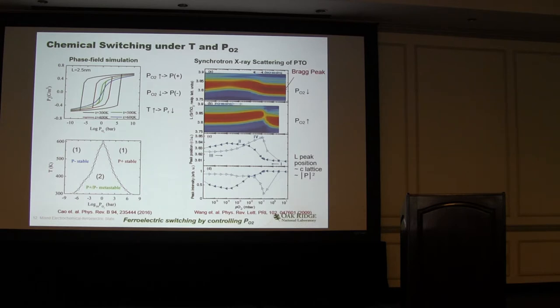this route. So when we plot the peak position and peak intensity as a function of oxygen partial pressure, we get a hysteresis behavior, which is typically seen in ferroelectric materials. Experimentally and theoretically, we find an effective way to control the polarization switching, including the chemical environment in this model.